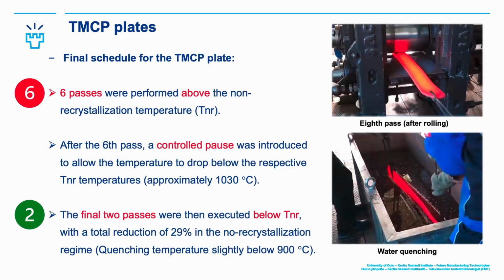Okay, so moving to the TMCP plates. From the previous study, we concluded the optimized schedule, and the schedule was selected to have 6 passes above the TNR, which is the recrystallization temperature. And then after the 6th pass, we have a controlled pause for reaching the temperature below the TNR, which was around 1030 degrees Celsius, and then using 2 final passes below TNR with a total reduction of 29%, and the final quenching temperature was slightly below 900. Exactly, it was 890 for the final quenching step.